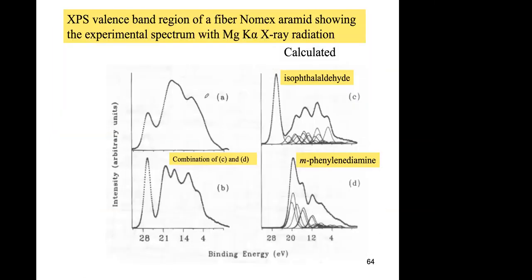There are handbooks. Actually, Physical Electronics has a handbook of valence band spectroscopy of polymers. These are calculated. This is the real one. But you can use your valence band spectra, and with spectra of different polymers, you can determine the concentration of each polymer. So it's like a fingerprint of the different polymers. And when you combine, for example, the calculation for this polymer, and you produce this valence band spectra, it's pretty close to the spectra that you see. So you can, in principle, identify polymers by looking at the valence band spectra.